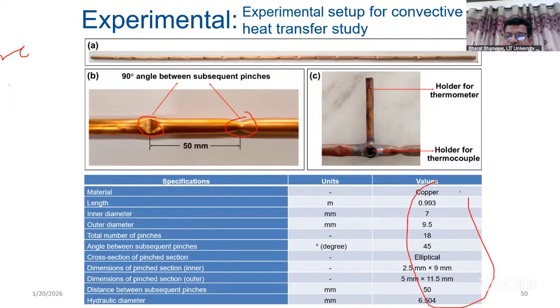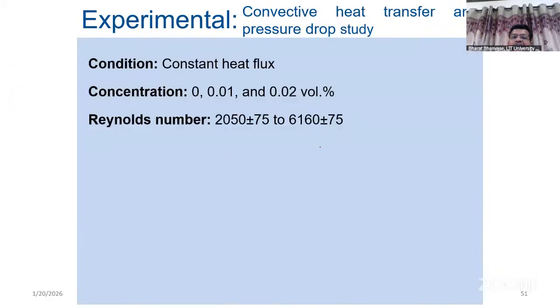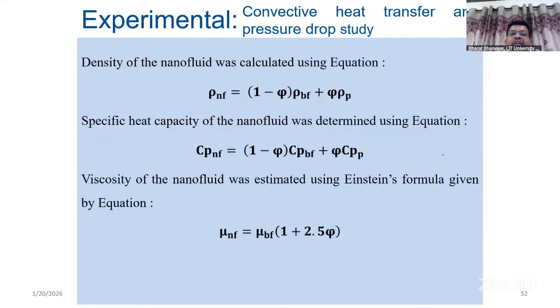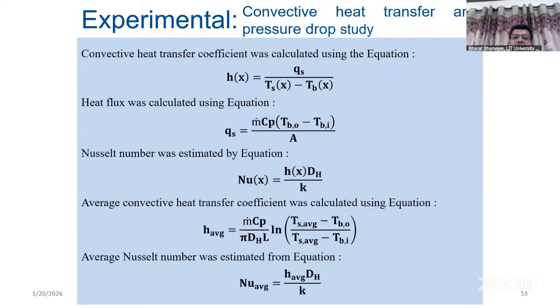Convective heat transfer study was done for two concentrations, 0.01 and 0.02 volume percent, with Reynolds number ranging from 2050 to 6160. Density of the nanofluid was calculated by this relation, where phi is volume fraction, rho BF is density of base fluid, and this is the density of particle. Similarly, heat capacity was calculated from heat capacity of base fluid and heat capacity of particle, with phi as volume percent. So heat transfer coefficient was calculated using this.